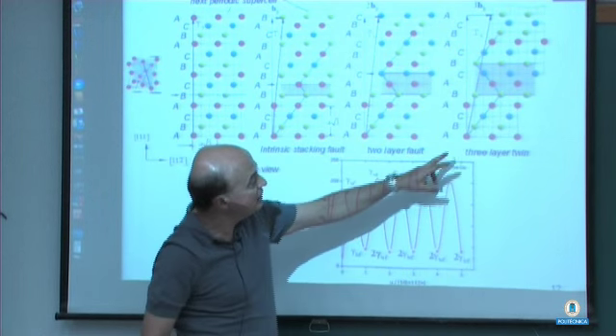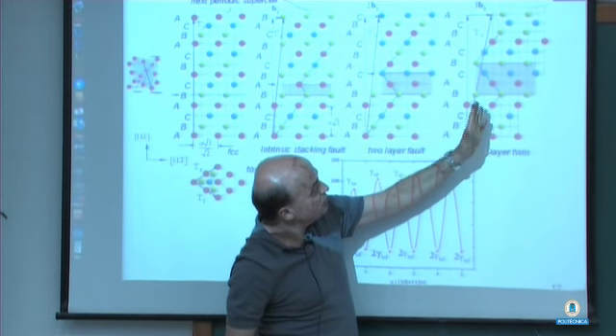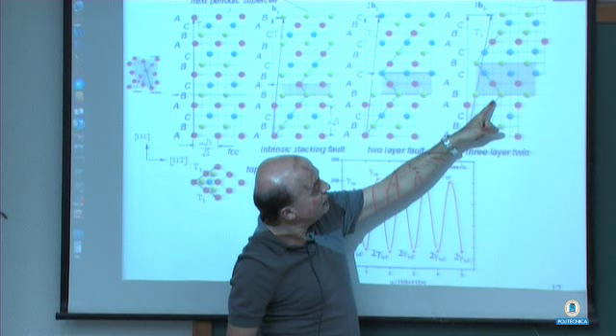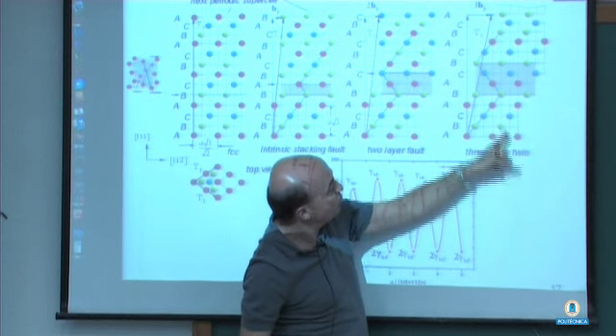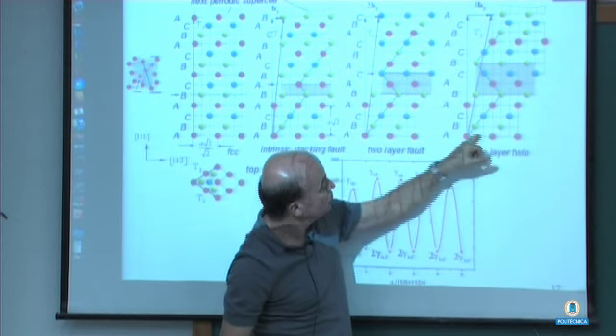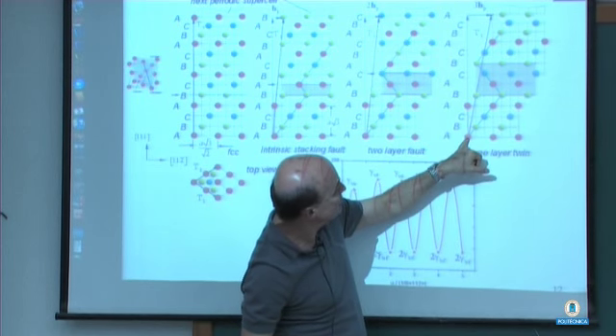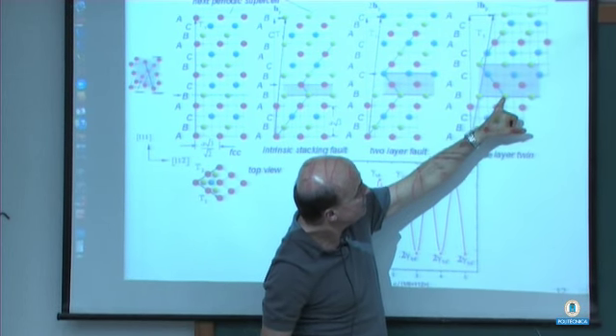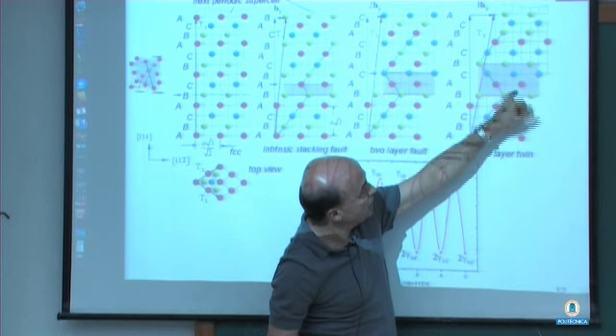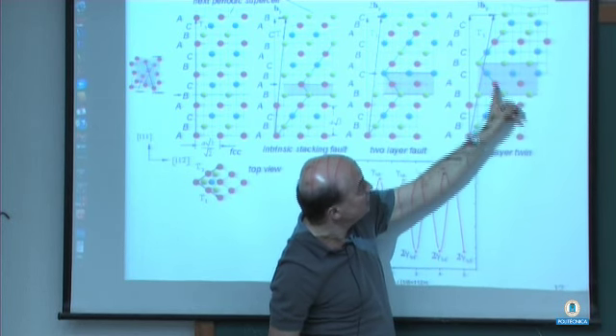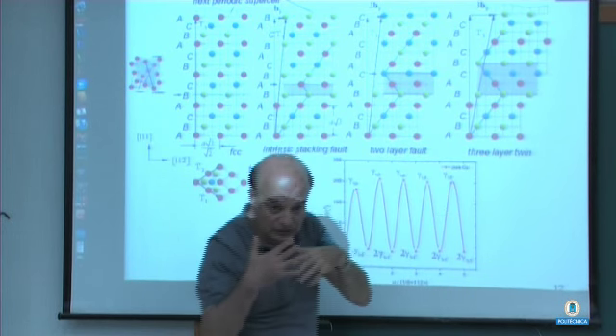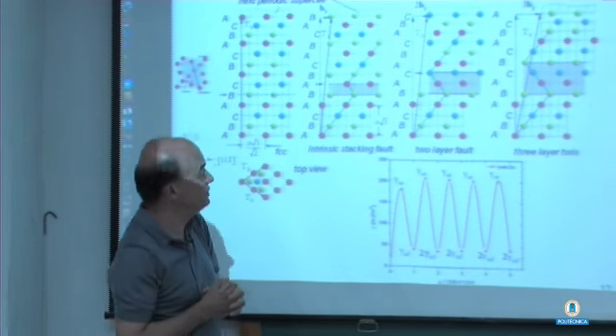And this is the final, for example, if I do this in the sequence that I describe, I will form a 3-layer twin. So what's happening here, as you note here, is that this is the FCC, and that's a twin boundary, and that's a twin boundary, and this is the twin. So I can create a twin in this fashion.